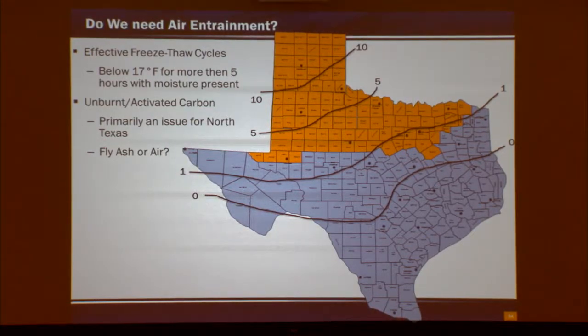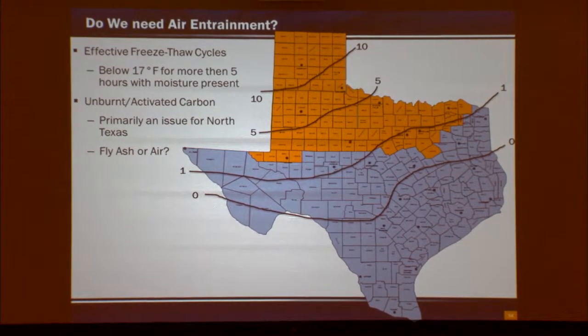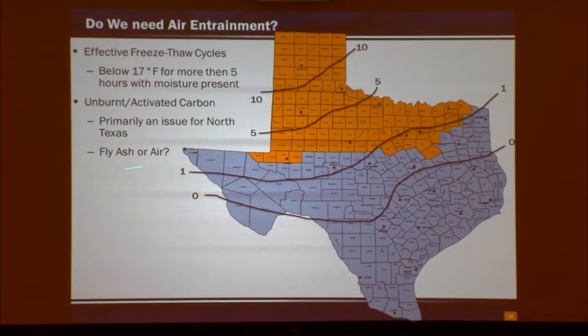So then you start dumping more air entrainer in there to get your air back up. Well, your next load of fly ash is good, and boom, you've got 10% air, and your strength tanks. And so we're always chasing this air content issue. So you northern districts really have to figure out, do I want fly ash, do I want air?